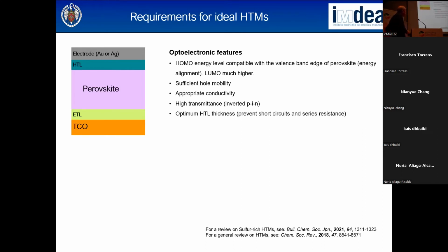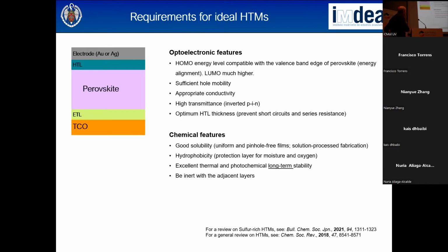Hydrophobicity is important because the hole transporting layer is not only for promoting the hole movement through this single layer to the electrode. It is also very important to protect from moisture and oxygen. The perovskite is, in this regard, much more unstable. You also need excellent thermal and photochemical stability, and to be inert with the adjacent layers, otherwise you get reactions. This is important.